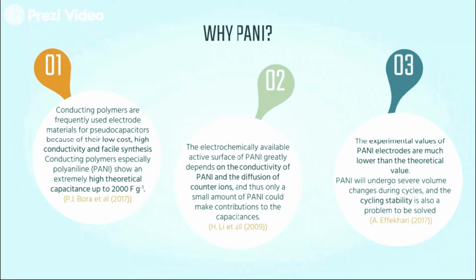So actually, conducting polymers are frequently used electrode materials for pseudocapacitor because of their low cost, high conductivity, and facile synthesis. Conducting polymer, especially polyaniline, show an extremely high theoretical capacitance up to 2000 farad per gram. And the electrochemical available active surface of PANI greatly depends on the conductivity of PANI and the diffusion of counter ion, and thus only a small amount of PANI could make contribution to the capacitance. So it actually leads to our second limitation, in which the experimental value of PANI electrodes are much lower than the theoretical value. PANI will undergo severe volume changes during cycles, and the cycling stability is also a problem to be solved.